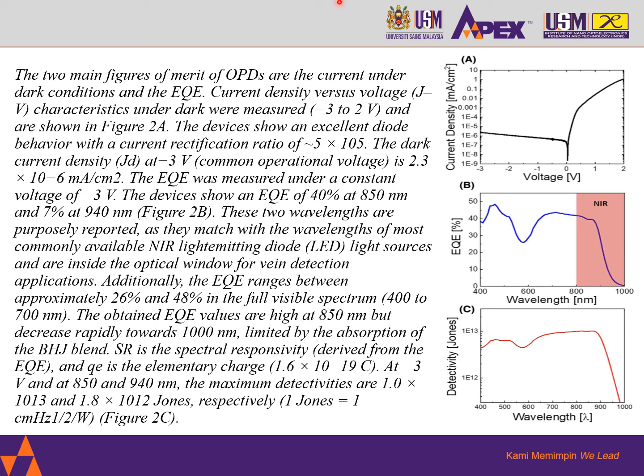The external quantum efficiency, or the EQE, was measured under a constant voltage of minus 3 volt. The devices show an external quantum efficiency of 40% at 850 nanometer and 7% at 940 nanometer, which is shown in figure 2b. These two wavelengths are purposely reported as they match with the wavelengths of most commonly available NIR light emitting diode, LED, light sources and are inside the optical window of vein detection applications. Additionally, the external quantum efficiency ranges between approximately 26% and 48% in the full visible spectrum, 400 to 700 nanometer.